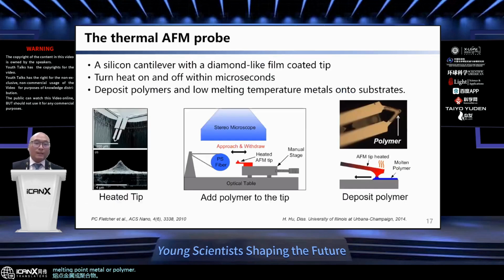Okay, so when I became his PhD student, my first project was to expand the application of this thermal AFM probe. This is the special AFM probe developed in Professor King's group. It is a double-armed silicon cantilever with different doping. At the tip region, it's lightly doped, so it's highly resistive, and the temperature is proportional to the resistance. So you can apply a very simple feedback loop to control the temperature of the probe at a desired set point by controlling the electrical resistance.